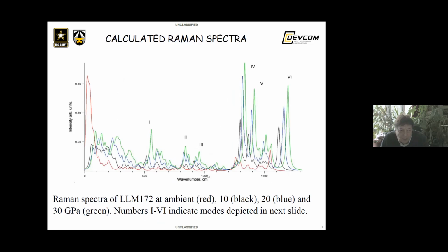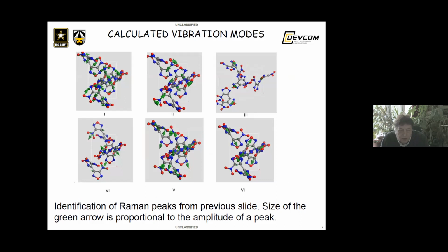The Raman spectra peaks are shifting to higher frequencies upon pressure, and this might be clearly seen from the figure, especially for the middle and high frequency ranges, the systematic shift. Here's a visualization of the vibrational crystalline modes from the dynamical matrix in terms of atomic movements. One may see that high frequency peaks are related to stretching of nitrogen, carbon, carbon, carbon bonds, whilst the low frequency region corresponds to quite complex collective modes.